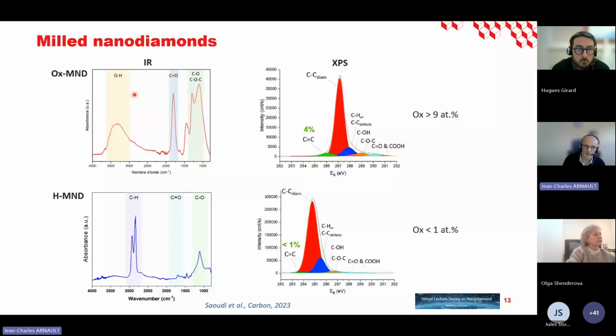So the oxidation or the hydrogenation, you have here the IR and XPS fingerprints. Perhaps I will focus here on the XPS. For the oxidized particles, you have an oxygen concentration of more than 9 atomic percent. You see that you also have sp2 carbon that is very significant in these particles. And the main component in the XPS is related to the C-sp3 diamond lattice. Switching to the hydrogenation, you see that we lose the oxygen. The concentration is now less than 1 atomic percent, and also the sp2 is considerably reduced to less than 1%.